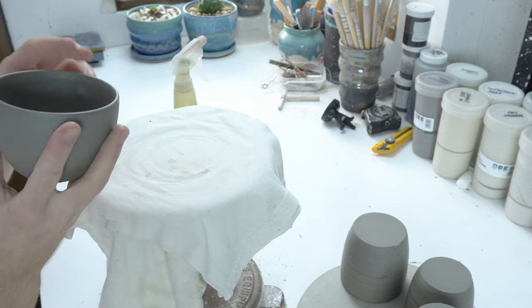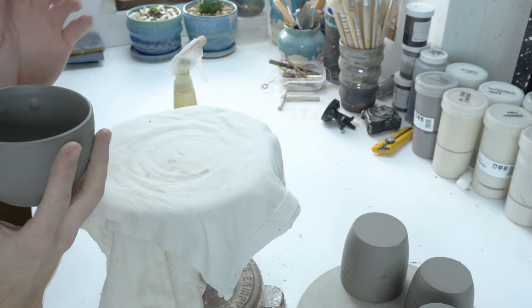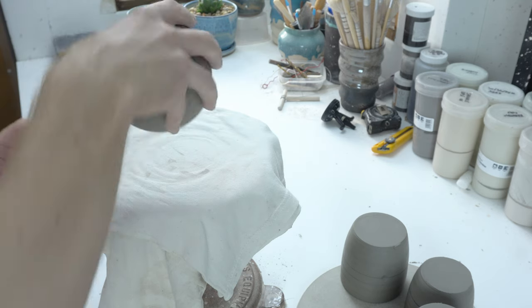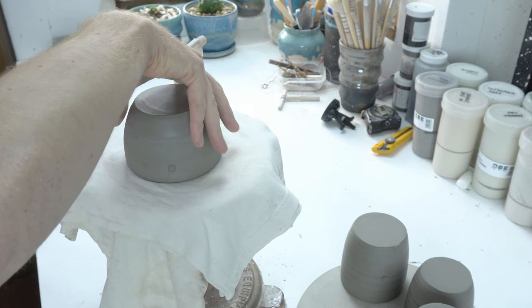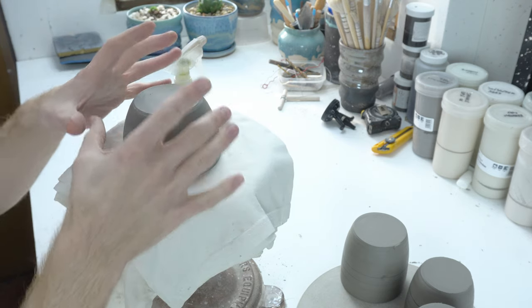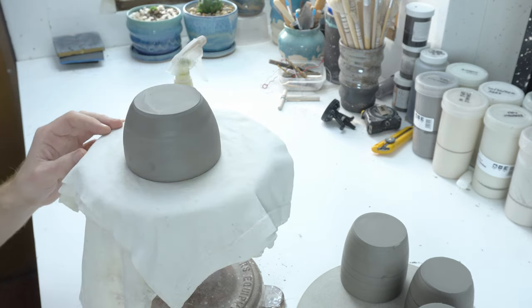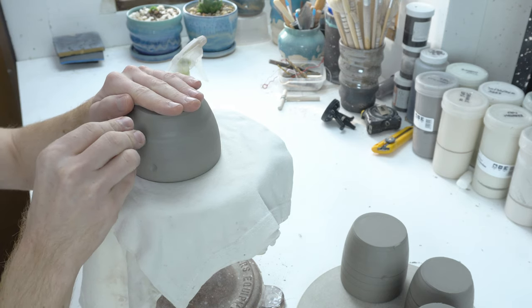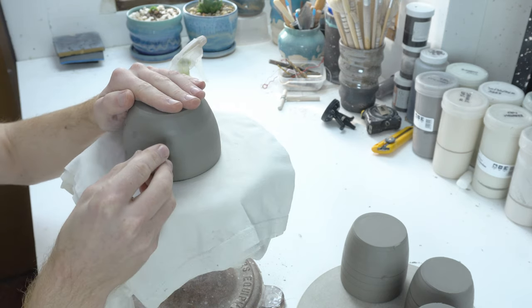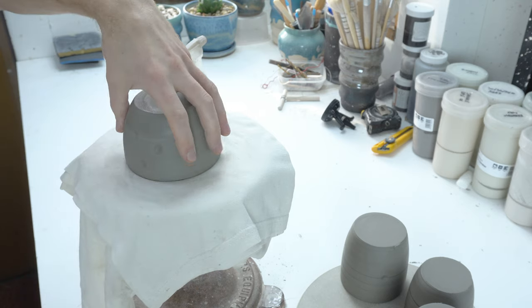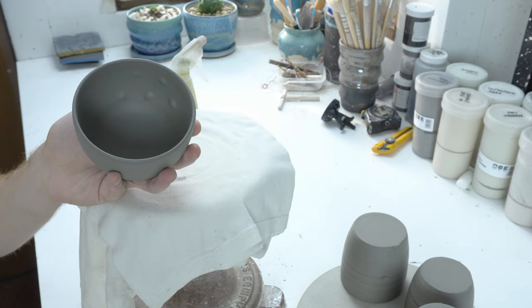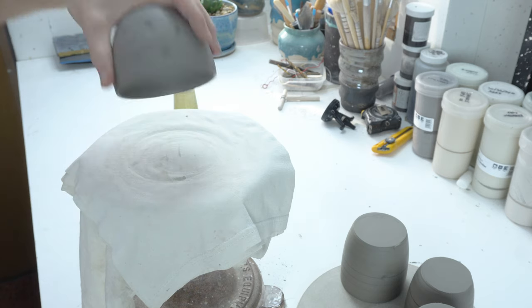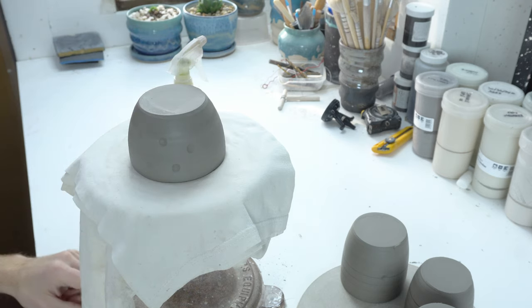And then assuming that's borderline firm enough, it doesn't have much water, then you can turn it back over and continue to stamp. And the outside remains as dry as it was. You get a good release. There's no sticking when it comes away. But the inside is stamped really nicely. So you can balance the two levels of dryness like that.